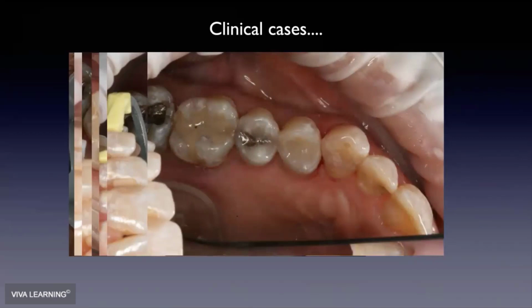And here it is after 2 layers, a little bit more of a dentin layer, and then finally an enamel layered composite. This is not some fancy composite I spent hours on with 5 different shades of materials and opacities and put pit and fissure stain in there. And you can see arguably that it looks very much like a natural tooth. It was delivered in all of 20 minutes or so.